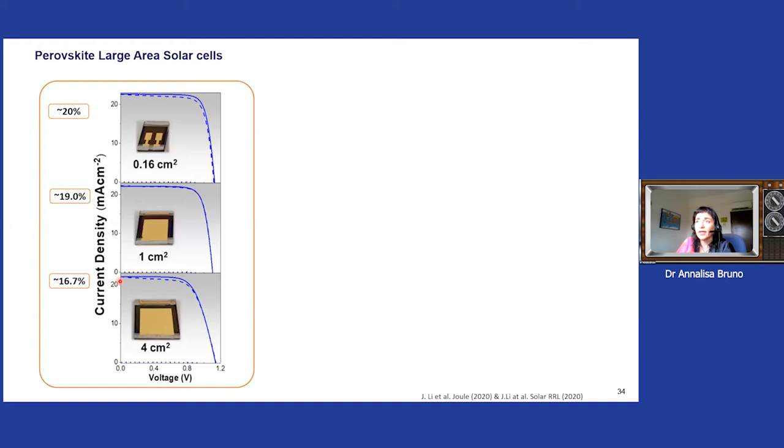Also, what you can see is the voltage, when you scan the voltage at open circuit, that is when there is no current in the device, also does not decrease, increasing the size. It is stable. So this means that the quality of the perovskite that we have in the whole cell is good. You observe here that there is a loss in efficiency. This is basically due to the decrease of this point here that corresponds to the fill factor of the curve. It decreases differently. And the decrease of the fill factor is related to the sheet resistance